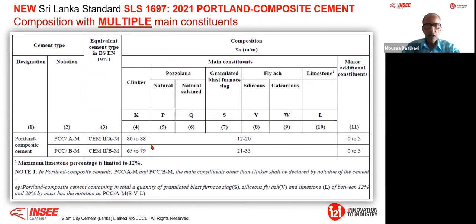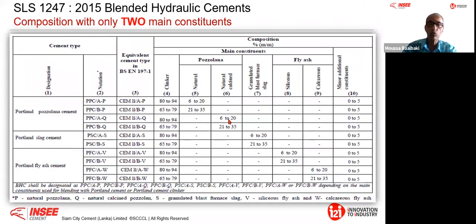Therefore, in the Portland composite cement, the producer has the possibility to mix different additions. I can mix, for example, pozzolana and slag and limestone, or fly ash and limestone, or limestone and slag. Therefore, I can mix with 2 variants, what we call PCC A or PCC B. The A means 12 to 20%, and the PCC B between 21 and 35%. The only difference for the A is that when I look at the blended hydraulic cement or the Portland limestone cement, there you start at 6 to 20.